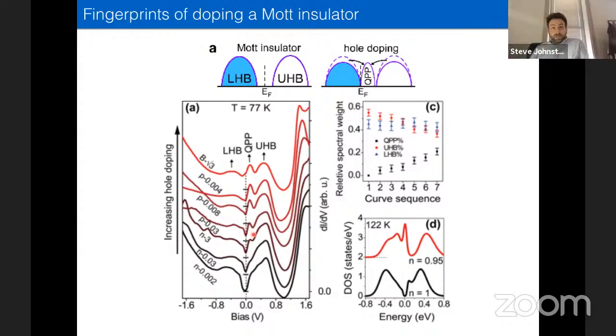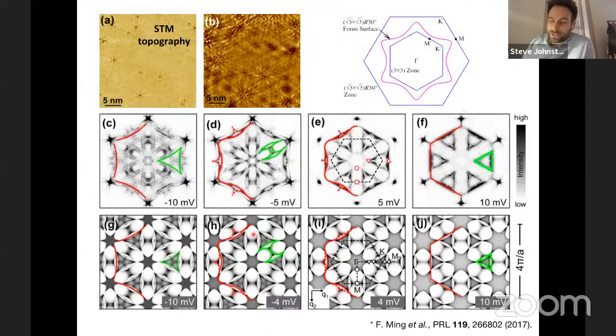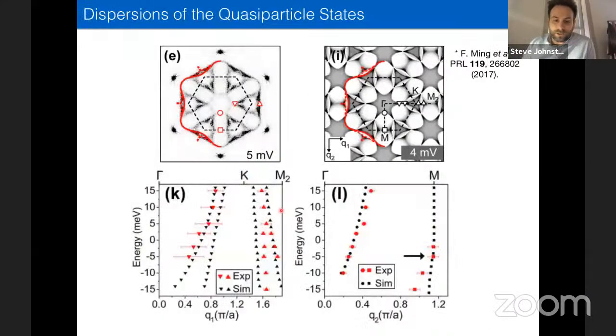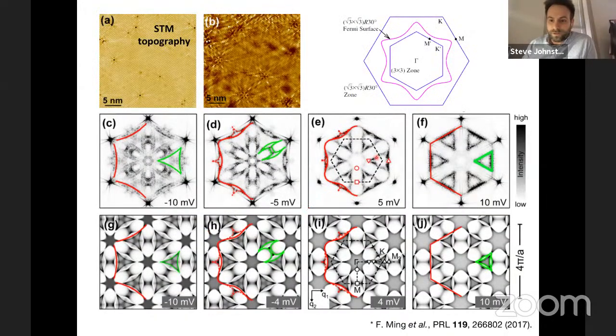Well, what I can do is I'll dig out the Z values we actually get from the DCA calculations. I'll give you some hard numbers if you let me get back to you on that. But my suspicion is they're actually going to be pretty small, or it's going to be close to 1. And the reason why, and I actually found this quite surprising, is that the dispersions of these quasiparticle states actually agree fairly well with what we get from just the non-interacting band. So somehow, the states nearest the Fermi energy don't seem to be renormalizing significantly, with the exception of these peaks here. These contours get flattened quite a bit relative to what's seen in the calculations.